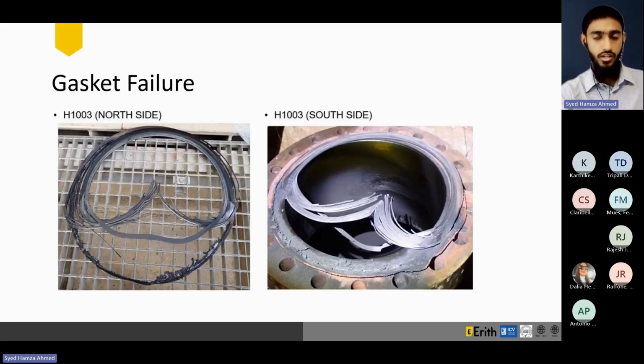was torqued at high values. However, they did not use any hot bolting. The torque value recommended was 574 Newton meters. In terms of foot pounds, it's about 424 foot pounds. But the values used at the installation were almost double that. And the reason stated was to avoid retorquing, to avoid hot bolting later on.